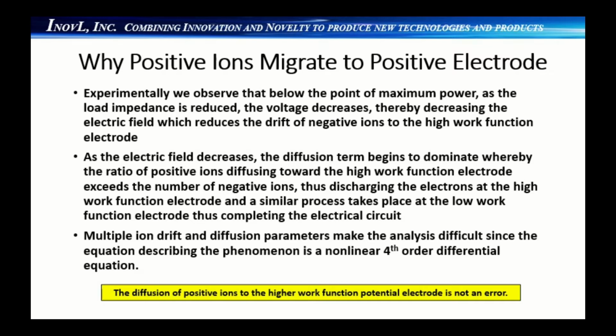In reality, multiple ion drift and diffusion parameters are involved. In fact, even for the simplest contact potential difference devices, the equations describing the process are a fourth-order nonlinear differential equation which does not have an analytic solution, and the LEC is not one of the simplest contact potential difference devices. We are currently working on a technical note that goes into more detail describing these ion dynamics. The bottom line is that diffusion of positive ions to the higher work function potential electrode, as shown in the previous slide, is not an error.